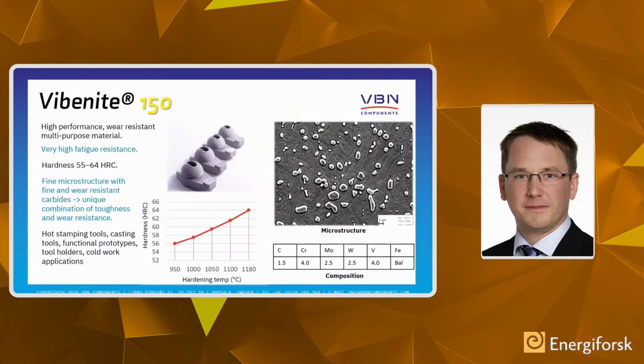We look into another alloy. This is the Vibinite 150, which, as I mentioned, is the softest alloy that you have today before we release the new alloy. This is also a wear-resistant, very fine-grained material with very fine carbide content. So also this is a very interesting alloy. And what we have seen is that we have a very, very high fatigue resistance thanks to the cleanliness and the fine microstructure in the material.